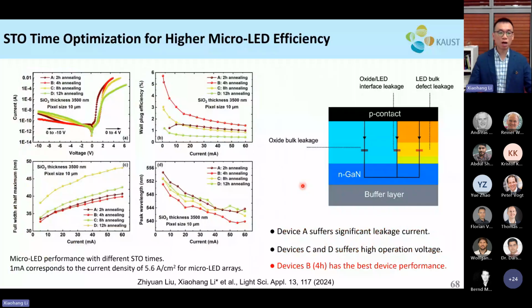So here I show how the different annealing temperature affects the LED performance, because here you don't want to anneal too little, right? Because if you anneal too little, you only anneal part of the P-GaN, then you don't form a very good isolation of the pixel. But you don't want to anneal too much, because if you anneal too much, there will be some lateral diffusion of oxygen into your pixel, right? So that will affect your device performance as well. So eventually, by comparing the wall-plug efficiency, we found that the device with 4 hours of annealing shows the best device performance compared to over-annealing or under-annealing.